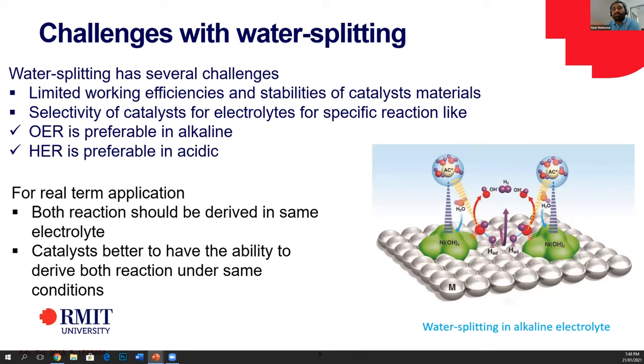If we need to make it efficient, we need to do it at lower energy consumption, which is where the catalysts come in. Catalysts help us do this at lower energy, but these catalysts still have a lot of challenges. At the current time, we have developed a lot of better catalysts that can do this at very low energy consumption, close to the ideal situation. But all of these catalysts still have selectivity. Some are selective for OER, the oxygen evolution reaction in water. Some are very selective for the hydrogen evolution reaction. Some are also very selective towards the medium in which they work: some are very good in alkaline, some in acidic mediums. So we need something that can do both reactions in the same medium.